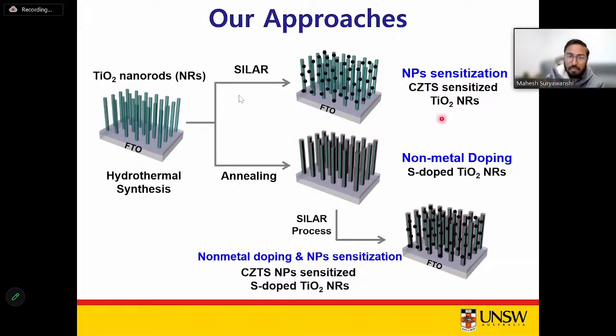First one is nothing but nanoparticle sensitization, which is the quantum dot sensitization with copper, zinc, tin, sulfur quantum dots, because this compound has a band gap energy of 1.5 electron volt, and is very famous for thin film solar cell application. That means it also has the capability to absorb the maximum sunlight and can be used for hydrogen production. Also, as I said in my previous slide, non-metal doping, because doping sulfur into TiO2 nanorod arrays will add additional energy levels into the TiO2 band energy that will reduce the band gap of the TiO2 to absorb slightly in the visible range of the sun spectrum. And finally, combining both of these strategies together to have a double or synergistic impact on the performance.